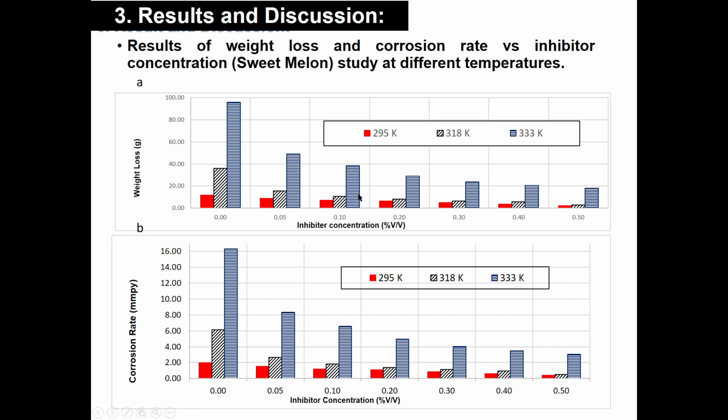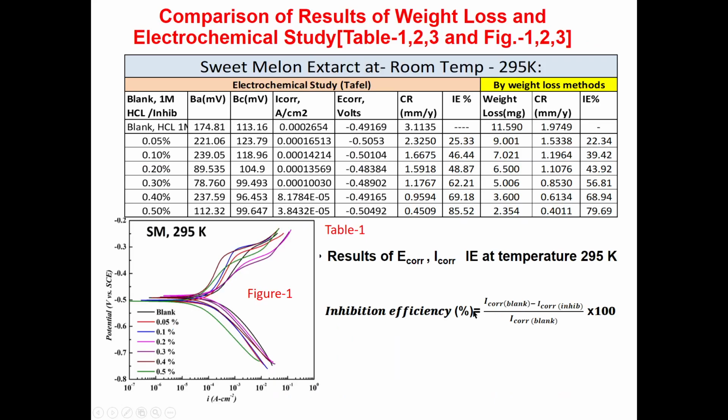If you take any one concentration, with the increase in the temperature you can see that the weight loss is increasing. A similar behavior is observed for the corrosion rate at different temperatures. This is the data from the electrochemical study and the comparison with the weight loss method.